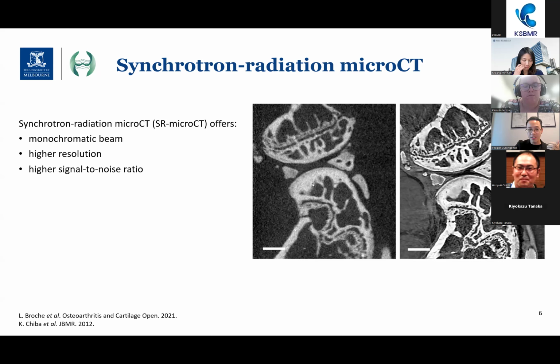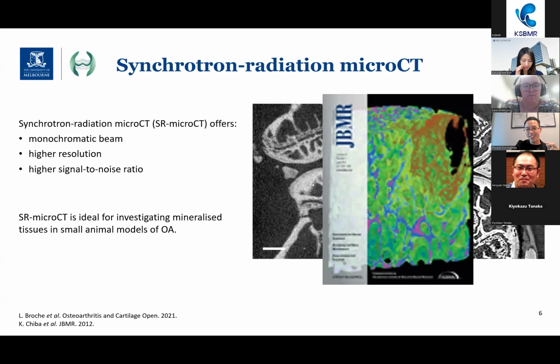And in terms of mineral density, I can show you that it is great, as my friend here was featured on the cover of JBMR a few years back. Here we can get the metabolic activity of the bone, where you can see the layers in orange showing the abnormal metabolic activity of the bone around the lesion area. And we can only get this level of contrast between normal and abnormal metabolic activity with a synchrotron monochromatic beam.